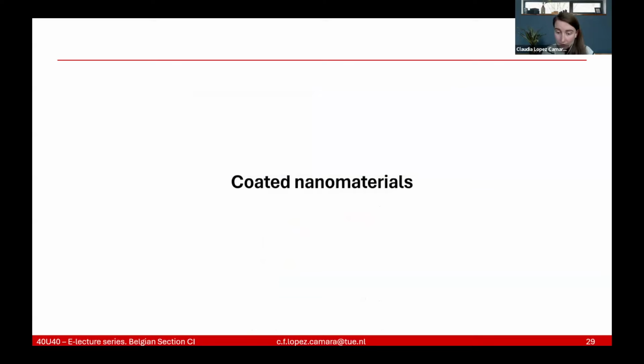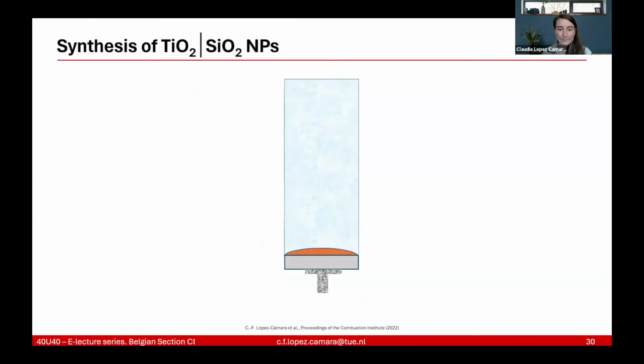So going into the coated materials, because now we saw some sort of coating, but now we will be looking into coating nanomaterials using a flame reactor. In this case, we wanted to use titanium dioxide and study the best way to coat it, which is the best coating that we can create, or which is the best precursor that we can use for creating a silica coating. And for that, we put together a flame reactor. Here you see a quartz tube, and at the bottom it's a flame, it's a burner, sorry.